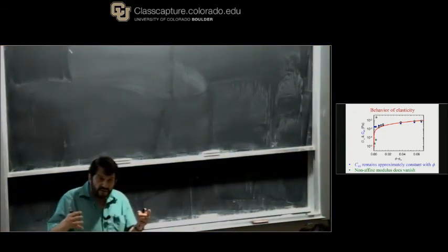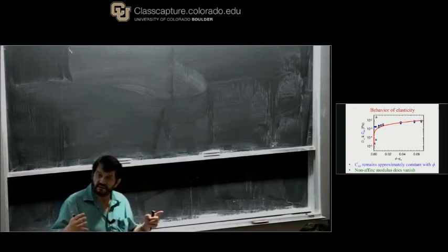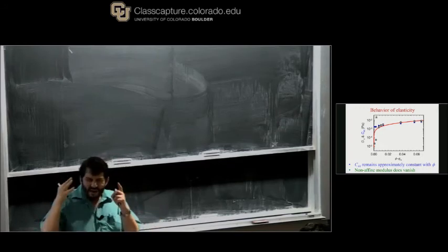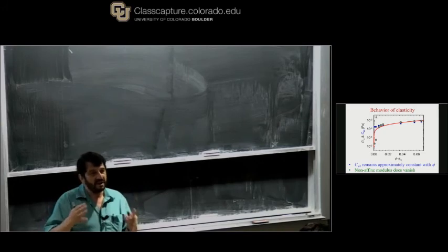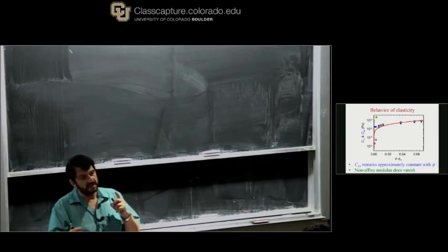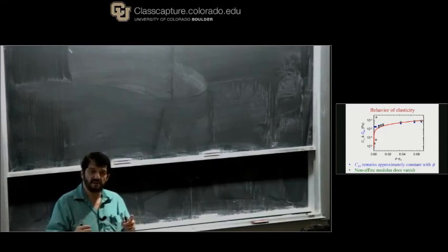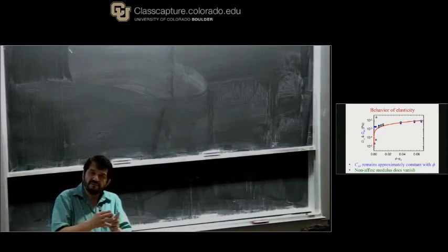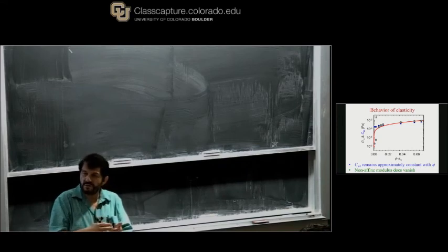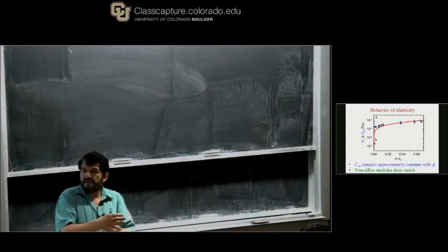But the critical thing here, the beautiful thing here, is that you can actually see melting in what's almost the damn closest you'll ever come to seeing melting of a solid to a liquid that's almost second order. It's not quite, but it's almost second order. It's very, very weakly first order, and that's because this is where you're preventing melting. You're killing all the interfaces.